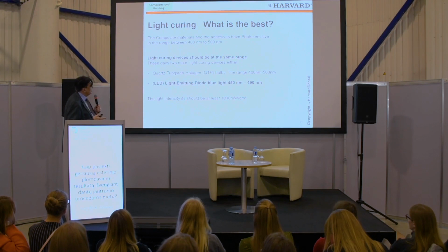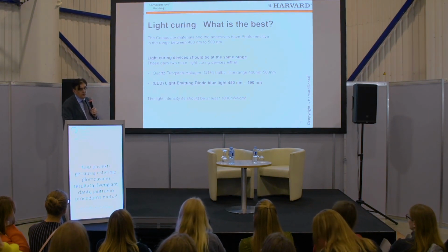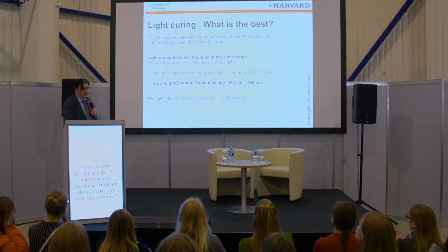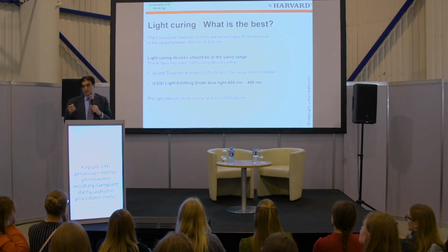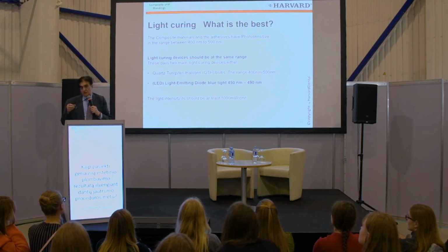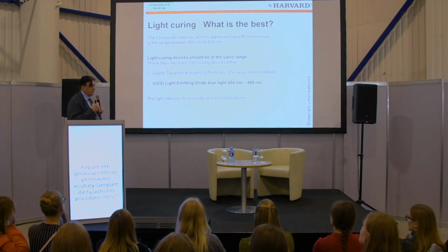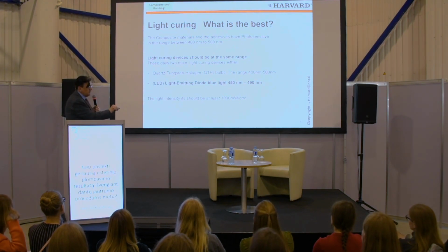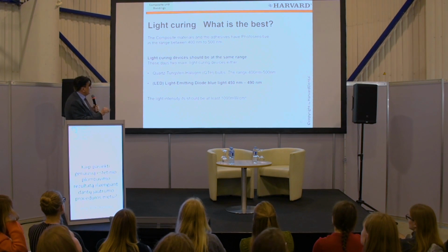Now the light curing, for me, is a very important instrument if you are using a composite filling material. As a dentist and as a practitioner, when was the last time you calibrated your light cure? After 5 years, 10 years, never calibrated? How do you know that your light cure device is working? For our composite filling, it should give you a light intensity of 1,000 milliwatts per square centimeter, and the range should be 400 nanometers to 500 nanometers.